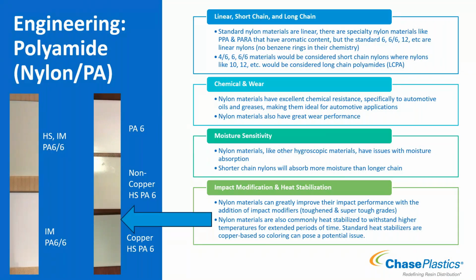All the way here on the left, you've got a heat stabilized and impact modified - this would be a super tough grade. You can see it's a little bit deeper in color versus the more whitish color of the non-heat stabilized version. Then here we have a standard 6 - a non-copper heat stabilized 6, and a copper heat stabilized 6. You can see as it goes down, it changes and gets a little deeper in color, a little more discoloration. All things I like to point out, so we're aware that's what happens, and it's pretty standard for using heat stabilizers in nylon. It's worth noting.